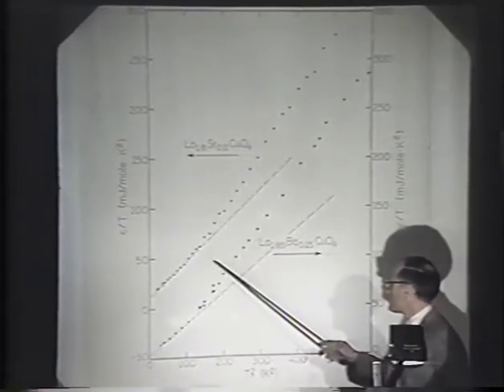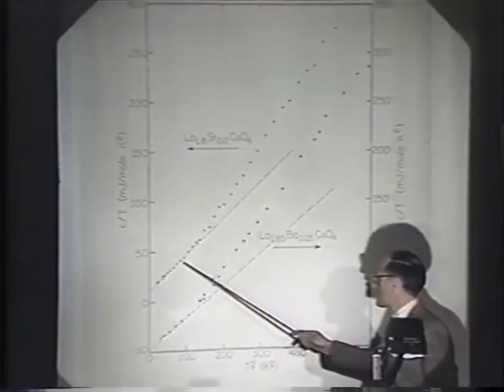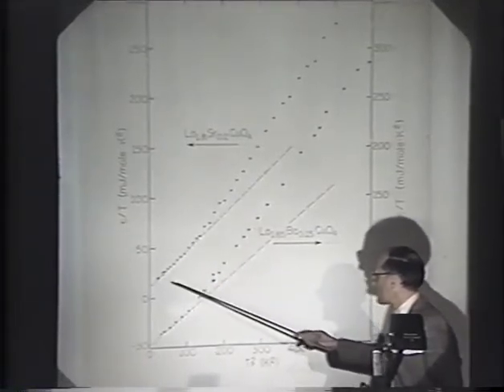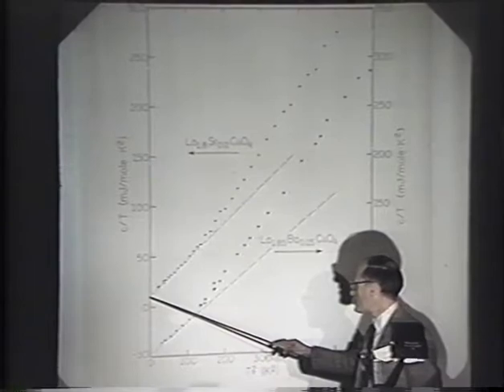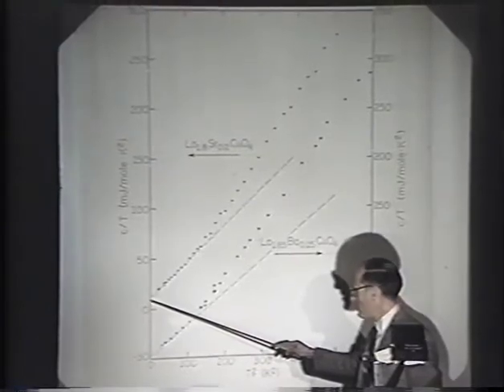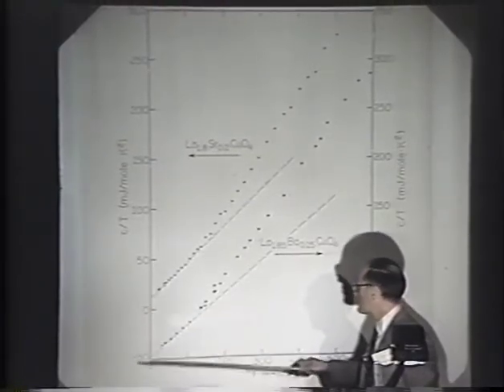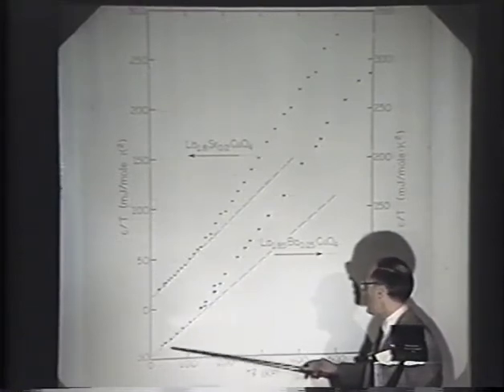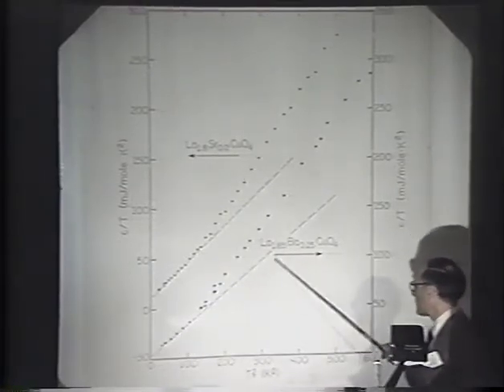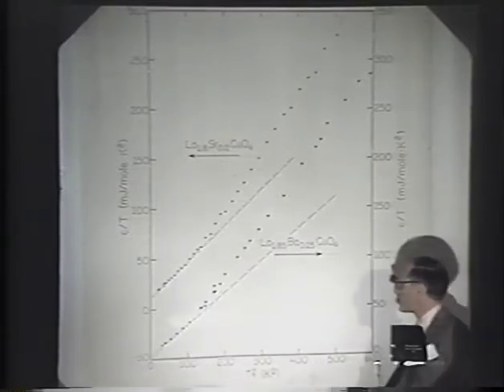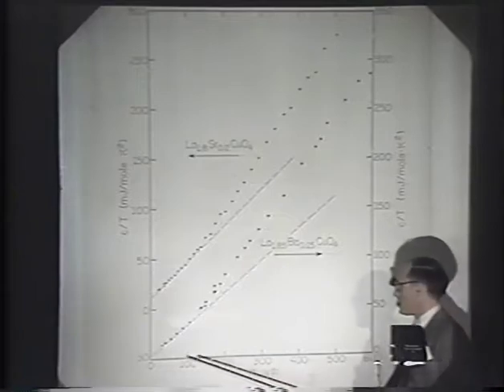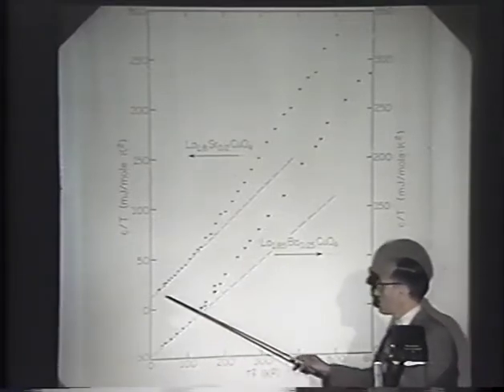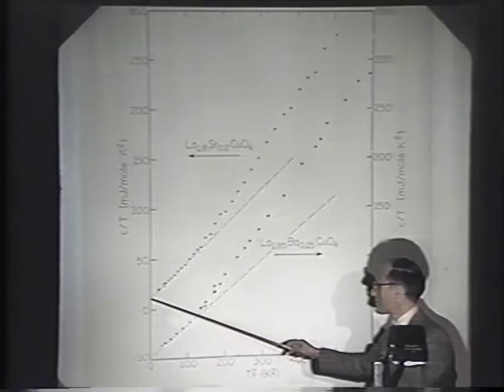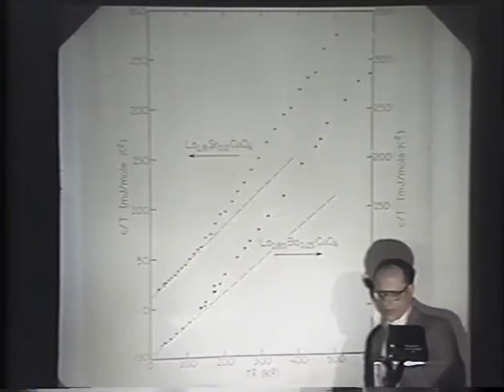This indicates, according to our analysis, that the electronic specific heat would be the intercept here, which is about the same as the previous speaker mentioned, about 5 or so millijoules per mole degree squared in the case of the strontium compound. In the case of the barium compound, with the right-hand axis, the intercept is very small, so there's very little apparent gamma value. We interpret this intercept for the strontium compound to mean that there's probably still a little bit of the sample that's in the normal state.